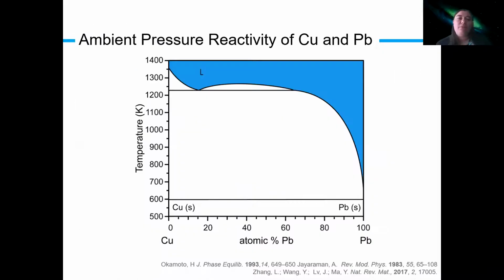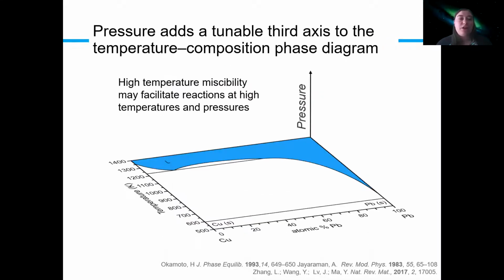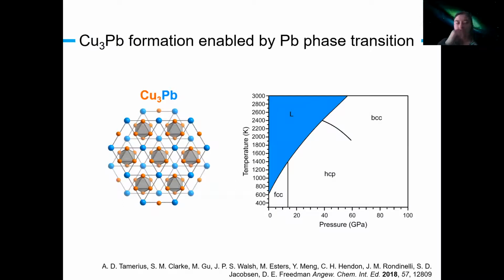And at the beginning of my PhD, the first place I started was with copper and lead. And copper and lead, at pretty low temperatures, they become miscible liquids. And so my hypothesis was that when you go to high pressures, that might enable you to form new compounds. And in fact, one of the things that I found was that you do form a compound, but this compound is dependent on the phase transition from the FCC lead to the HCP lead. So the structure only forms once you go above that phase transition.